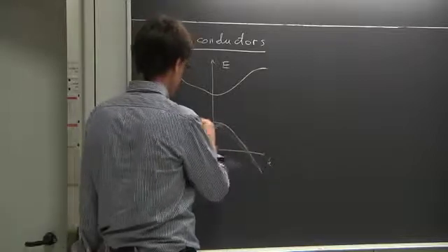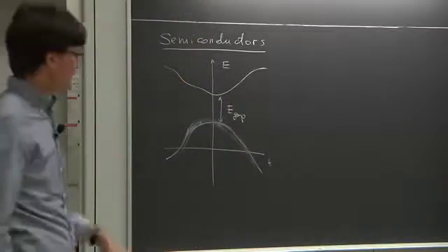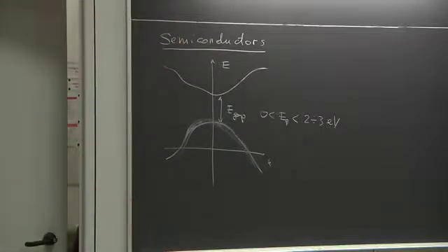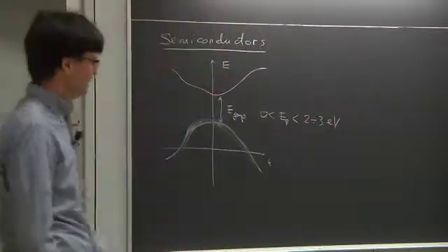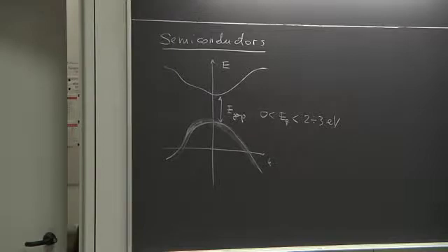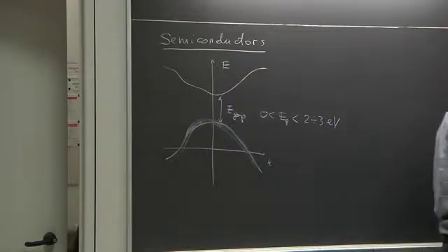So imagine a situation in which you have a band like this and a band like that, and this is completely filled, this is completely empty, so you have an energy gap which is finite, but it's not too big. And by not too big, we mean anything between 0 and, say, 2, 3 electron volts, depending on some properties. Anyway, something of less than a few electron volts, 2, 3, let's say. So technically speaking, these are insulators, but the gap is small.